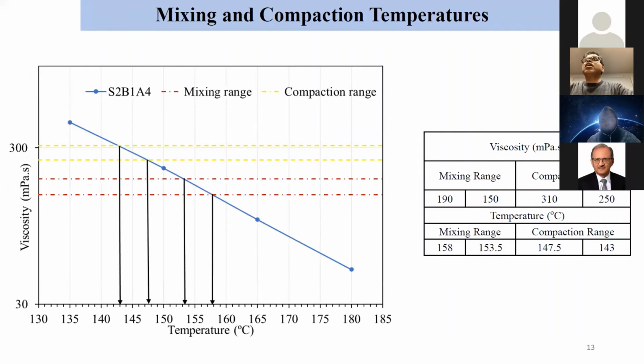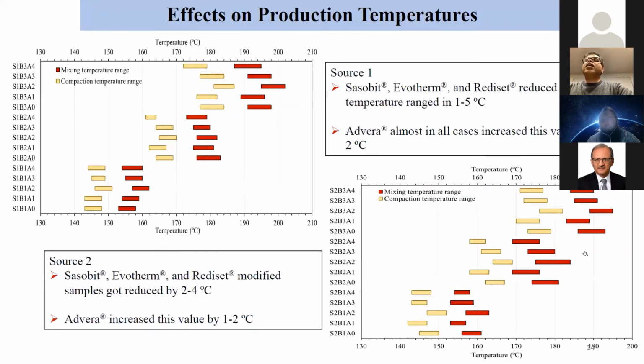And then compaction was 280 plus or minus 30. So that's why, from viscosity, we got 250 to 310. And from there we found the mixing and compaction temperature range.